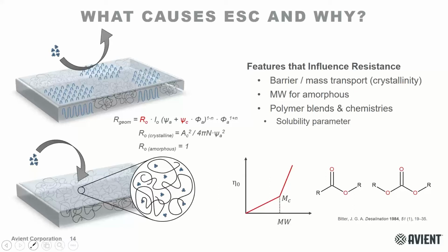So then what else can you do in terms of influencing the stress cracking resistance here? Well, number one is changing the solubility parameter of the system. And the ways that you can achieve that is through polymer blending or also through different backbone chemistries. Different backbone chemistries are going to have different solubility parameters, right? So if you're looking at, let's say, a polycarbonate, you might now switch to a copolycarbonate that's going to have a different chemistry that might show a little bit better diffusion resistance or overall lower solubility to the disinfectant that it's being treated with. Another way that this can be achieved is through polymer blends. So if you're blending in, for example, PBT into a polycarbonate, that PBT is going to, well, number one, it's going to bring some crystallinity, but it'll also change the solubility parameter of the system. So maybe a better example there is PET, rather.